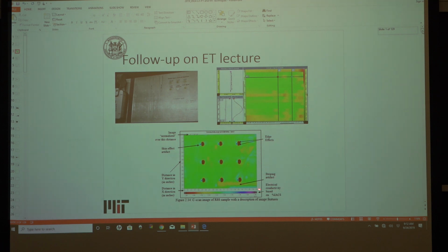You see a striping artifact down here. That is what happens if you do not go over the sample with a steady hand, and at some point some of the channels have a liftoff whereas others do not. You'll get the striping artifact because it's not going over the sample with the same force. There are ways that they can design this in with robotics and encoders.